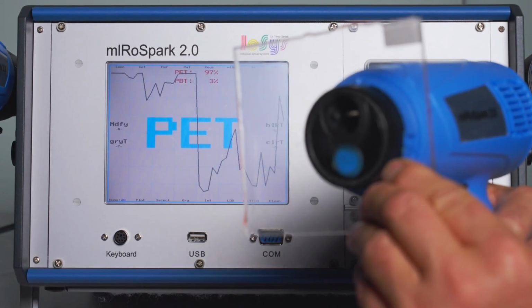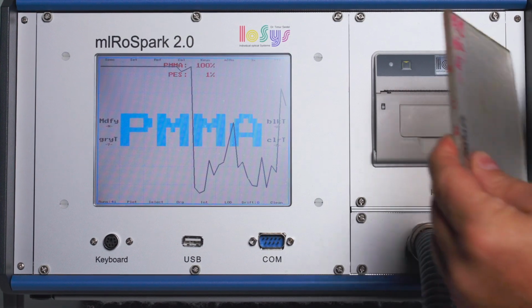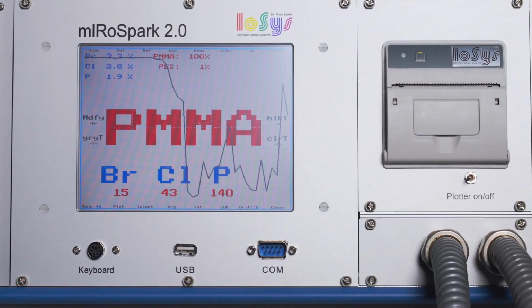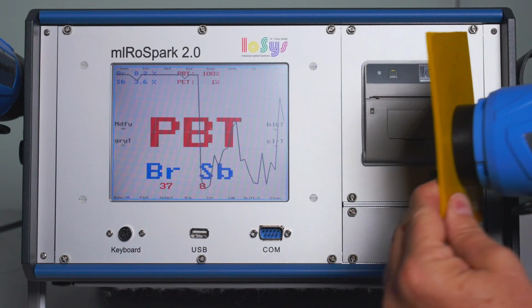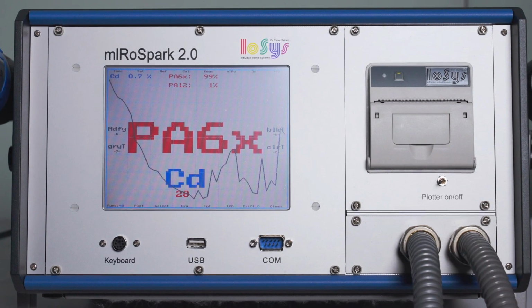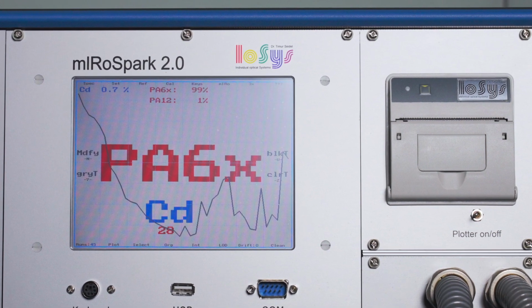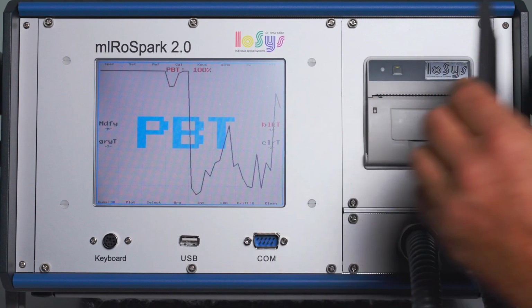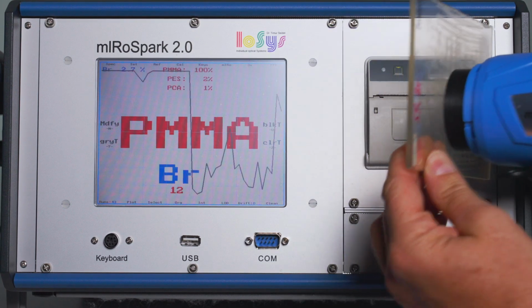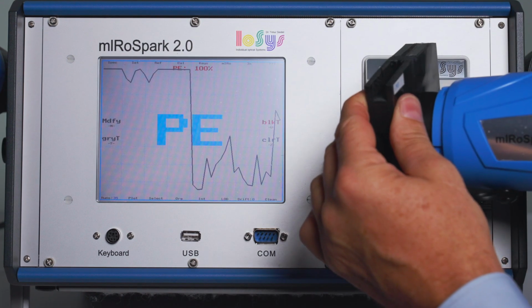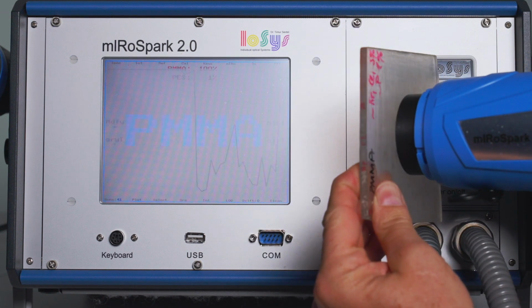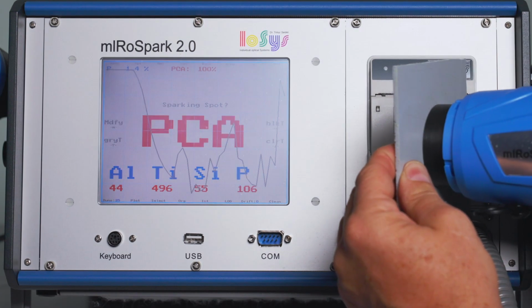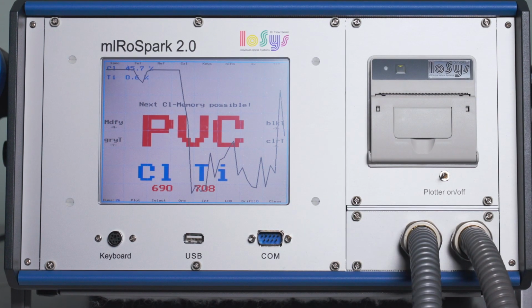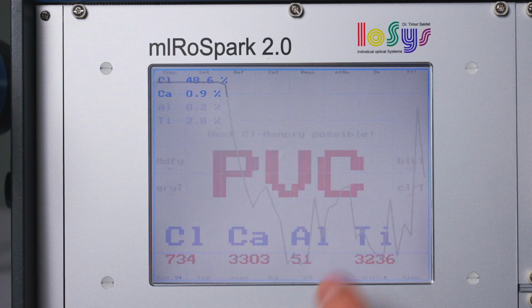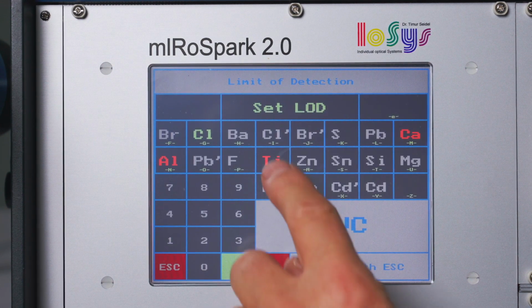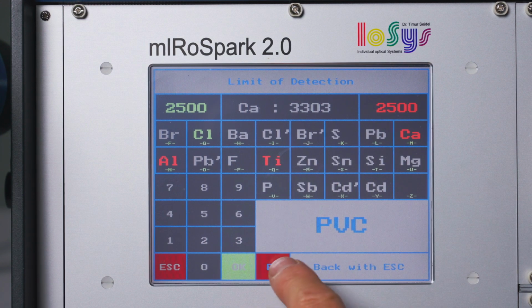If significant elements, for example recycling-relevant additives, are detected, such as flame retardants containing chlorine, bromine and phosphorus, or lead and cadmium as additives containing heavy metals, the measurement result is displayed in red. Additive detection is generally based on the characteristic atomic emission for an additive element in the optical spectral range. The intensities of defined spectral lines are compared with preset threshold values. An element is detected when the preset threshold value is exceeded. These LOD values can be defined individually.